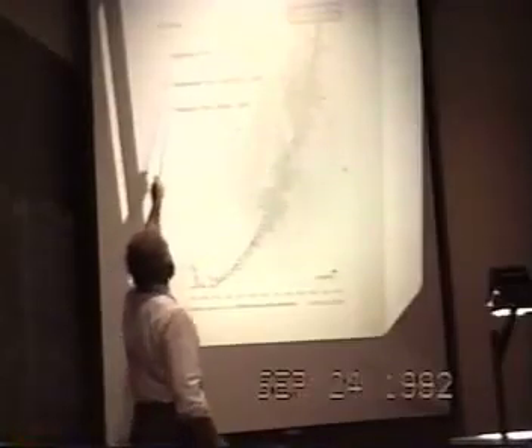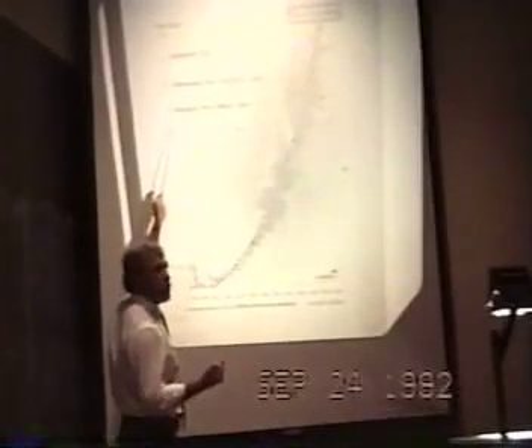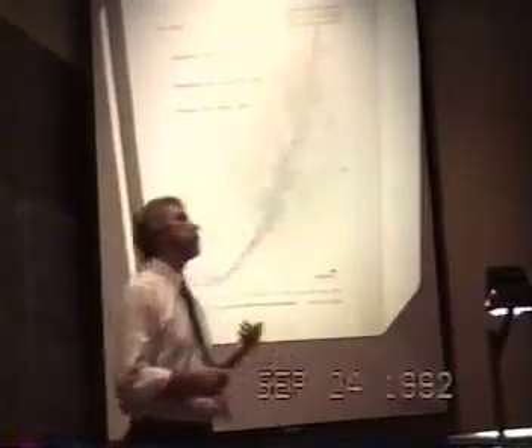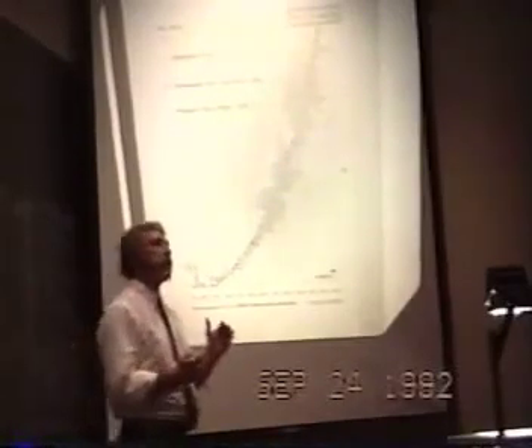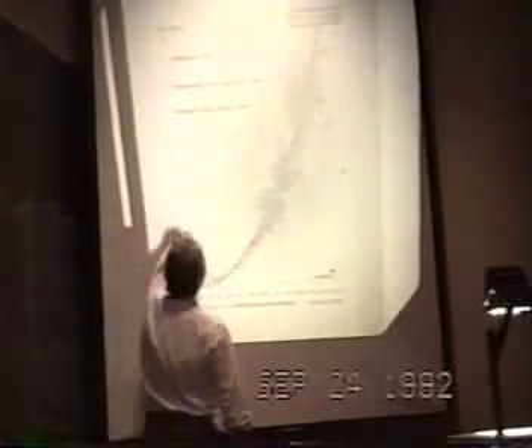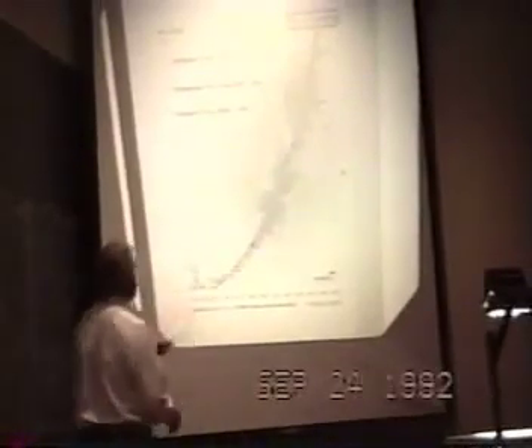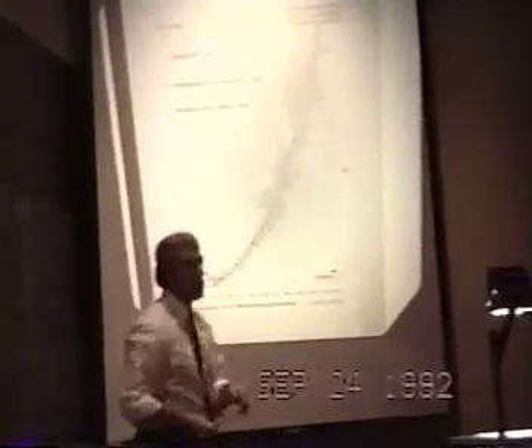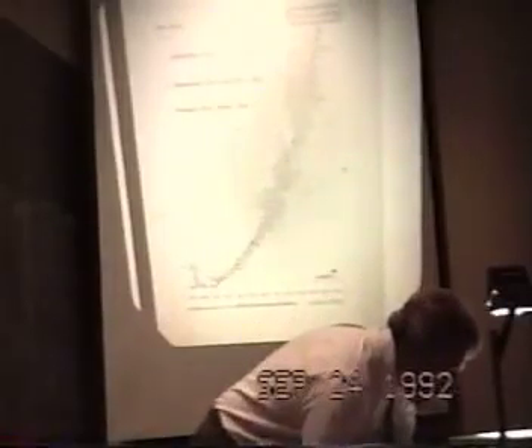An asymptotic function, asymptotic to a loading limit of 1, which you might expect if the parameter that we're observing is correlated to the activity of deuterium in the lattice. An exponential function, which you might expect if the observation of excess power is correlated to the population of a higher energy state, such as occupation of the tetrahedral sites in a Boltzmann distribution. And a parabolic function, which you might expect if the excess power observations are somehow correlated to two atomic interactions, the possibility of two species getting together above a critical threshold. The data are simply not good enough to distinguish between them, but there's clearly a correlation between the excess power observed and the loading.